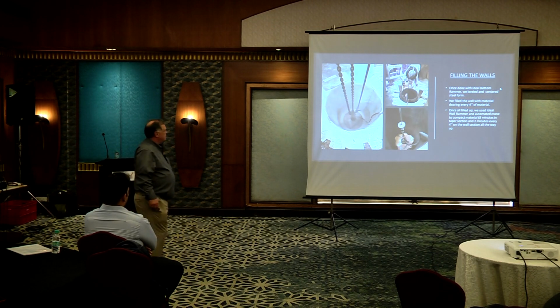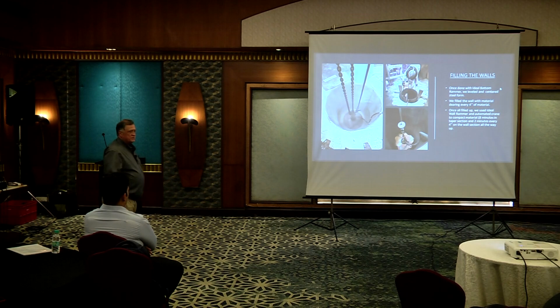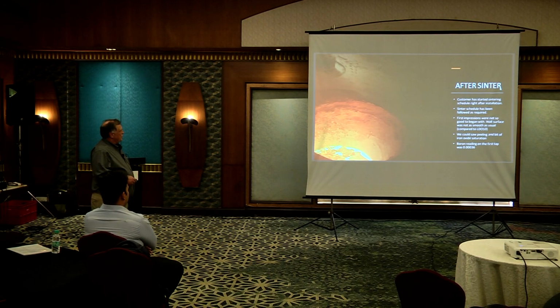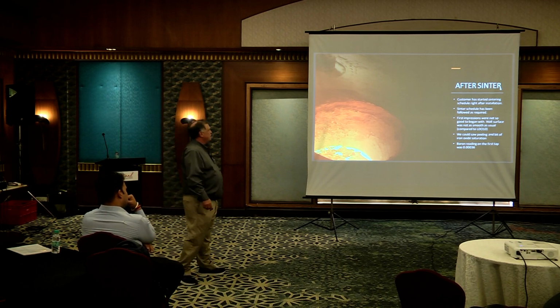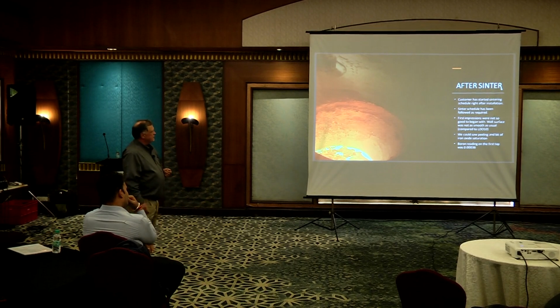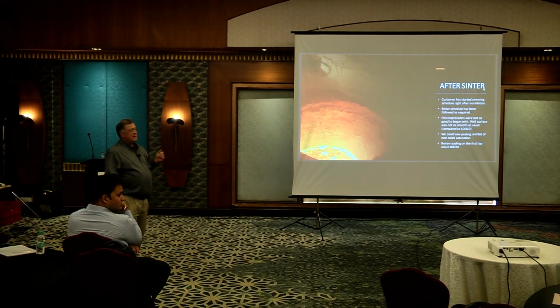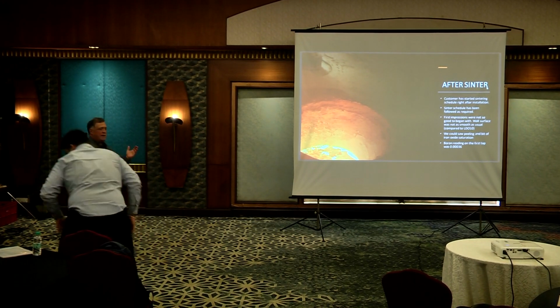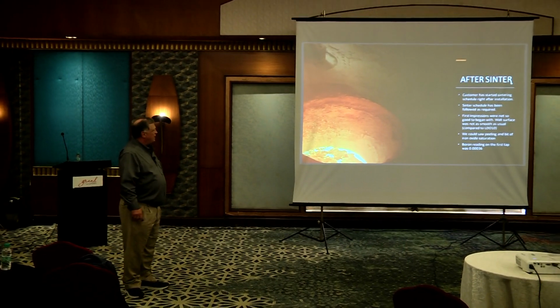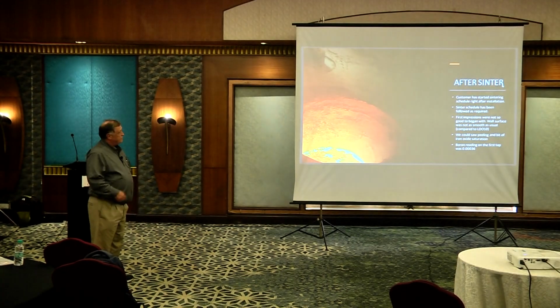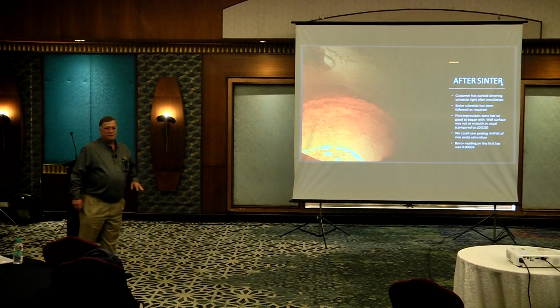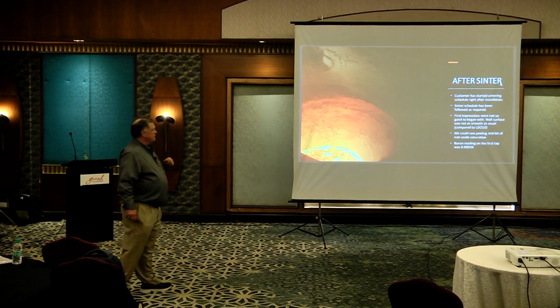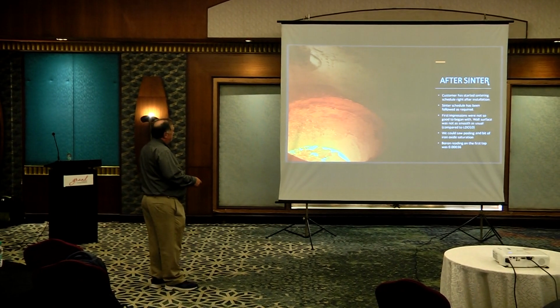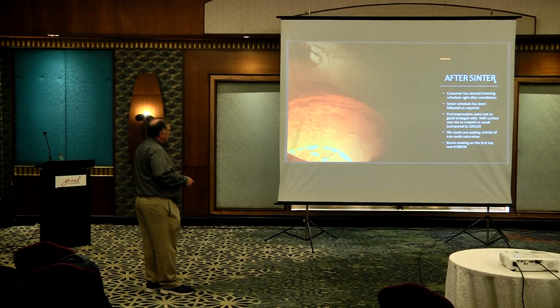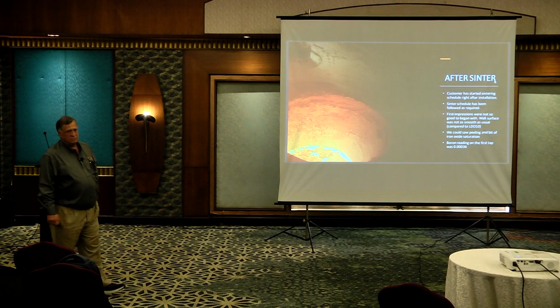So, as you can see, they're filling the walls. Basically the same process. There's nothing different as far as the installation goes. The installation process is exactly the same. Now, what they found, and this has been an issue in the early stages, is the customer started, they sintered it exactly the same way that they do in their standard linings, which is about an 18-hour sinter cycle with solid charge. And the sinter schedule has been followed as required by them, actually. The first impressions weren't good from this particular customer. In the initial hot face, you can see a little bit of peeling of the liner right down in here. And that peeling was very thin. It was skin, mostly, like a skin peeling.